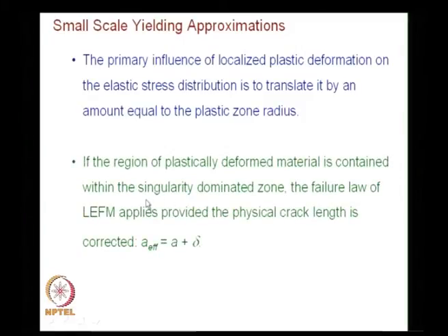And the third point is, if the region of plastically deformed material is contained within the singularity dominated zone, I can still apply the failure law of LEFM provided the physical crack length is corrected as A plus delta.